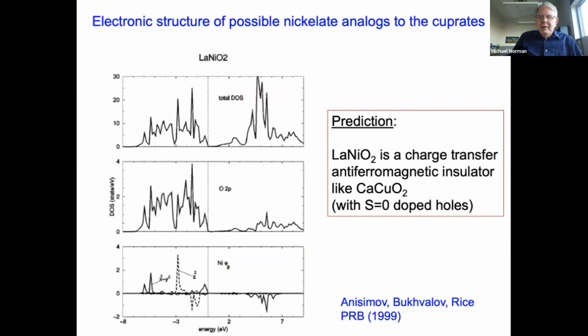So people have been thinking from a theory perspective about these nickelates for quite some time. One of the first papers was by Morris Rice and collaborators back in 1999, with the idea that they felt that lanthanum nickel O2, which is a 112 phase, would be a charge transfer antiferromagnetic insulator just like calcium copper O2. And then if you doped it, you would get spin zero doped holes very, very similar to cuprates.